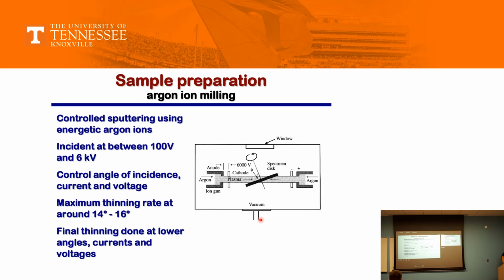Right? Now, ion mill. So what happens in the ion mill? It is one of the very common things. We call it tips. Here is your sample. In some experimental configurations, you rotate it. You have a plasma and you have an argon beam coming through. It's very automatic. You put it into the little sample holder here. You give your argon enough energy according to your sample, and that argon beam would slowly erode the sample from the center. So overall, you can have a controlled sputtering using energetic argon ions, with incident energy between 100 volts and 6 kV.